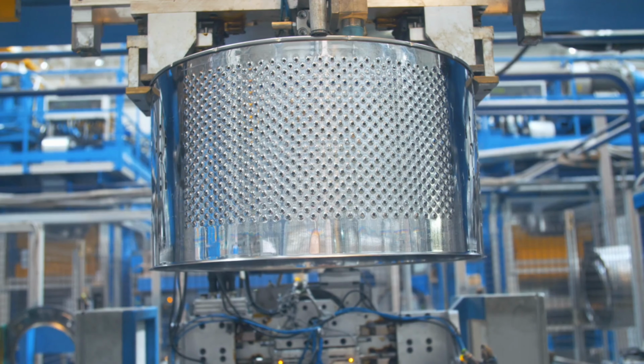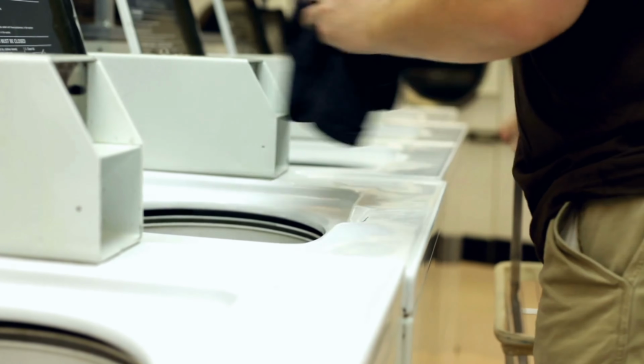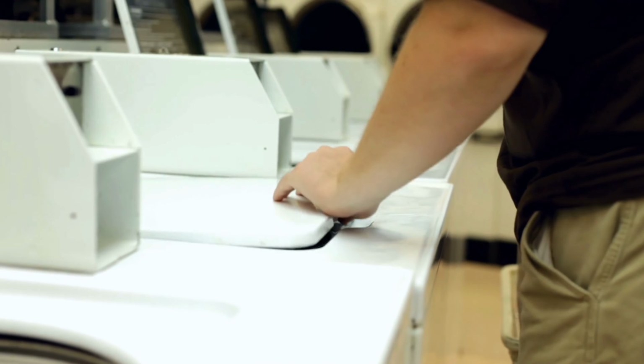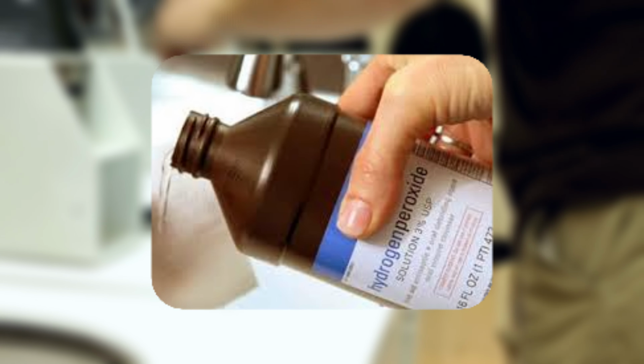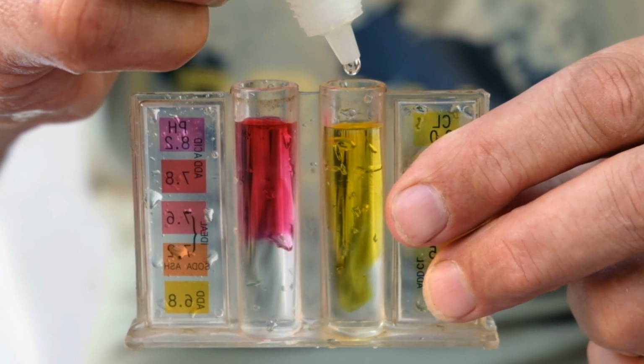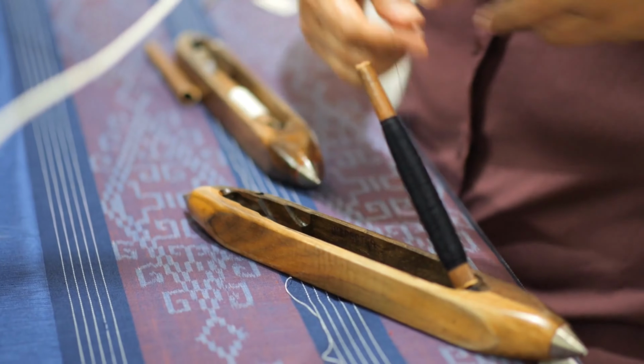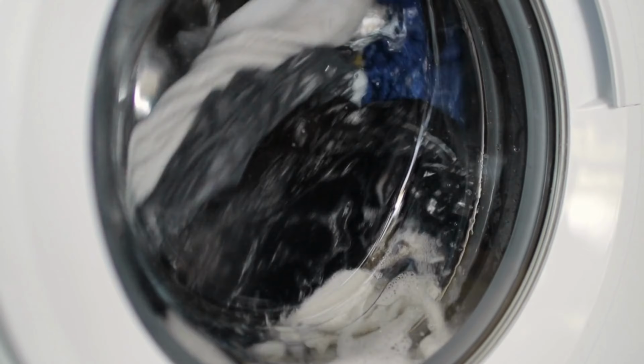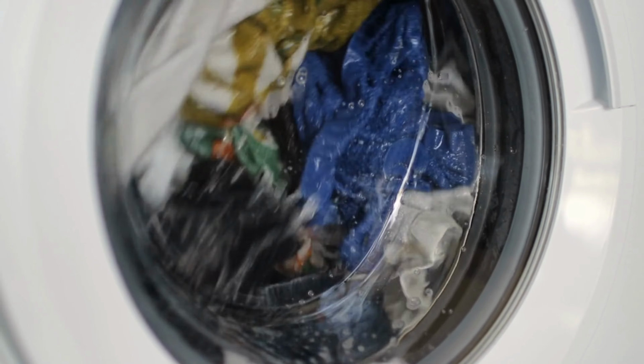Color removal from recycled fibers requires sophisticated chemical processes that can strip dyes without damaging the underlying cotton or wool structure. Bleaching systems use carefully controlled concentrations of hydrogen peroxide or sodium hypochlorite, with pH monitoring, ensuring that chemical conditions remain within narrow ranges that remove color while preserving fiber strength. The bleaching process can take up to 6 hours for heavily dyed fabrics, with multiple rinse cycles ensuring complete chemical